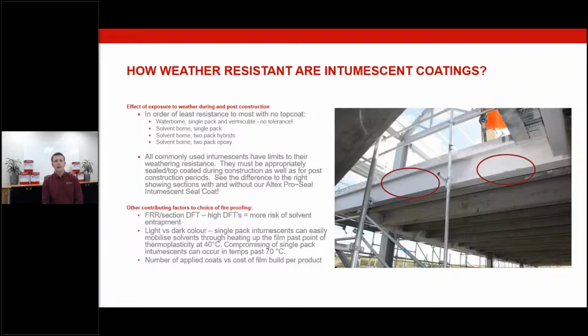You've also got light versus dark color. Single pack intumescents can easily mobilize solvents through heating up of the film past the point of thermoplasticity at 40 odd degrees Celsius. You start to actually compromise the single pack intumescent's ability to fully react past 70 degrees C. The coating chemistry itself, the actual intumescent coating, starts expanding past about 150 to 200 degrees C. But once you start going past 70 odd degrees C, the actual chemistry, albeit very slowly, starts to build. And once that chemistry is starting to kick into action, you start compromising the amount of time that you've got left in there.